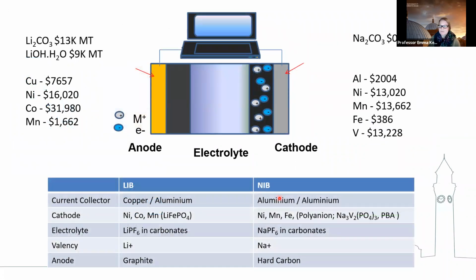So if we compare the components of the two different types of batteries, this is just an example of the battery. We have an anode, a cathode, and an electrolyte. And the anode is on a current collector, and the cathode is on a current collector. In a lithium-ion battery, the anode is on copper, typically. The anode is typically made of graphite as well, sometimes with silicon or silicon oxide in as well. And the cathode current collector is aluminium. Now, in sodium-ion, you could use copper and aluminium, but for cost reasons and for safety reasons, aluminium can actually be used as the current collector. And this is because in lithium-ion, lithium actually intercalates into aluminium at about 0.3 volts versus lithium, whereas sodium doesn't, so aluminium can be used in both.